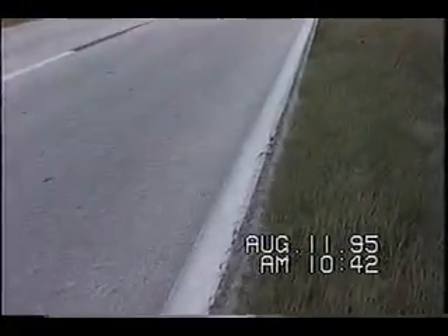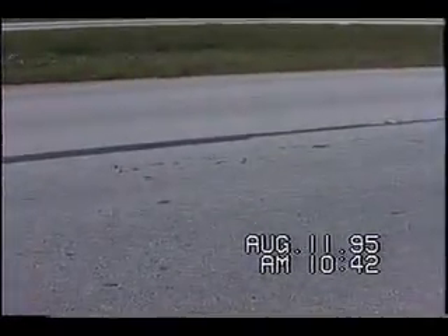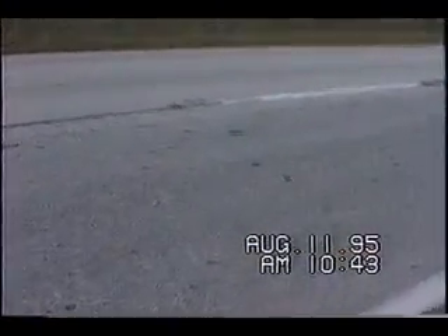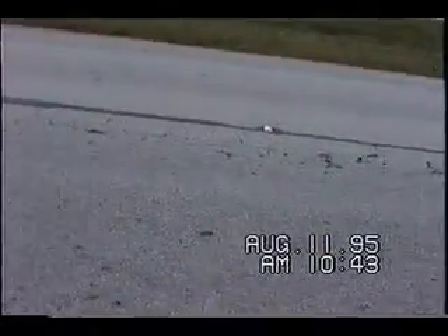Also here, as you can see, some spalling of the cracks. I deemed this high severity fatigue cracking because of the loss of material. There's a significant loss of material around the cracks themselves, and due to the fact that we have some pretty good rutting here, approaching 20 millimeters or so,